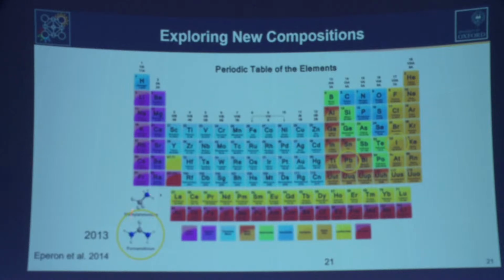If we want to go further, we can use formamidinium, the next size up in ammonium cations. That works, so we first reported formamidinium lead triiodide in around 2013, 2014. There are some advantages of formamidinium: it's slightly less volatile than methylammonium, and this seems really an important step forward for long-term stability of these devices.